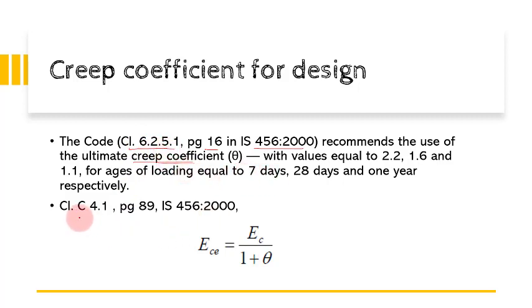Also note, for estimation of total deflection—that is, deflection because of immediate application of load and that which is occurring because of long-term effects of creep in the concrete member—the usual linear elastic analysis is made with reduced elastic modulus. This reduced elastic modulus is called effective modulus of elasticity. As per IS 456:2000, please visit Clause C-4.1—go to Appendix C, page 89—there you will find the formula for effective modulus of elasticity: Eceff = Ec / (1 + θ), where Ec is static modulus of elasticity of concrete, which is 5000√fck, and theta is your ultimate creep coefficient.